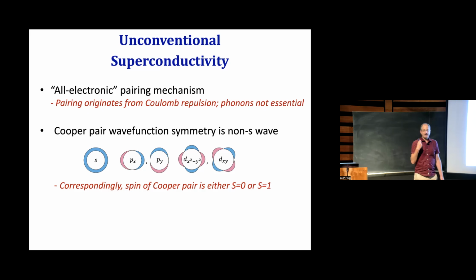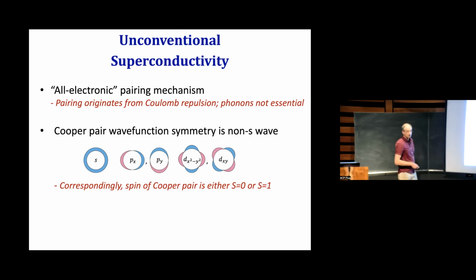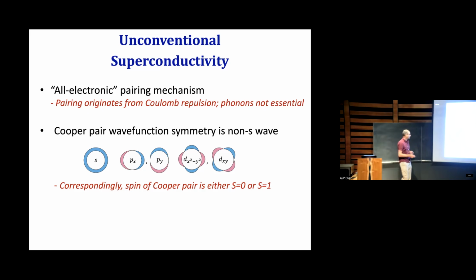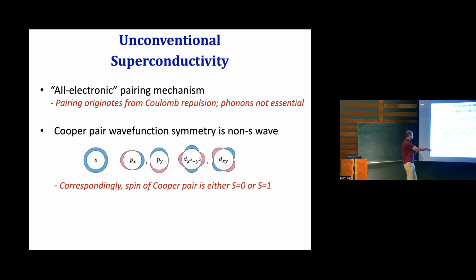In fact, one of the big triumphs of our field was the prediction and discovery of the pairing symmetry of the so-called cuprate high temperature superconductors, which is actually D wave. And this is something that you simply cannot get out of the conventional electron phonon mechanism. This was really a big advance maybe 30 years ago. And correspondingly, due to the Pauli principle, once you have a non-S wave relative symmetry of the Cooper pair, spin doesn't have to be zero. It doesn't have to be spin singlet. In fact, if it's odd angular momentum, it would be spin triplet. And I'll be talking about that as well.